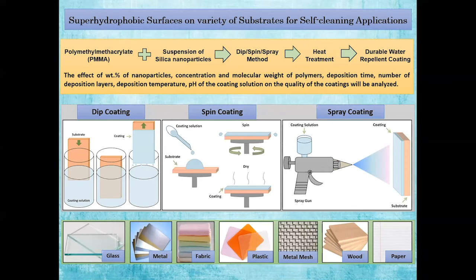We make a nanocomposite of different polymer and silica nanoparticles, and using dip, spin, and spray coating methods and subsequent heat treatment, we could form a water-repellent coating on different substrates like glass, metals, fabrics, plastic, metal mesh, wood, and paper. So there are many surfaces we have tried this composition on, which is PMMA and silica nanoparticles.